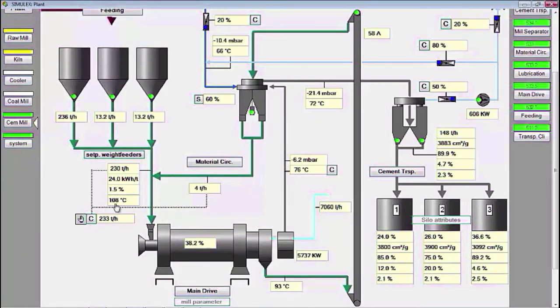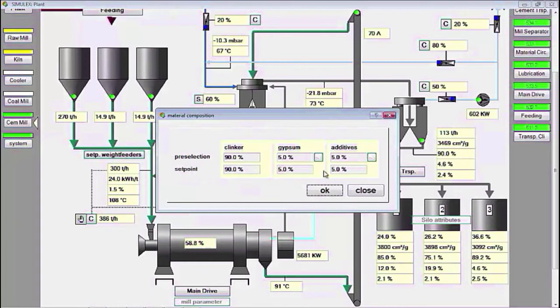This Blaine is too high, so we try to add feeding first, it becomes 300 tons per hour, and this is still a manual setting of the total sum feeding. This total sum feeding is the total of fresh feeding and tailings material, and currently we are setting 300 tons per hour. Blaine is currently low. For producing PCC cement, the Blaine standard is 3800 to 4000 square centimeters per gram of cement.